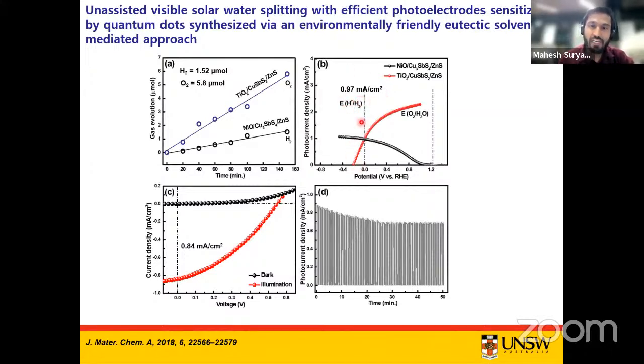That means we don't need an external bias to initiate this water splitting reaction, and hence we call it an unassisted water splitting system. By analyzing the crossover of the LSV curves from the photoanode and the photocathode, we fabricated the two electrode system and measured its performance. We achieved a photocurrent density of about 0.84 milliampere per centimeter square, which is close to about 1 milliampere per centimeter square. However, the slight decrement can be attributed to the resistance arising from connection problems.